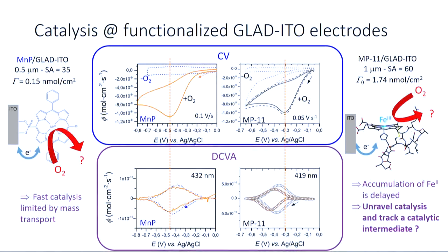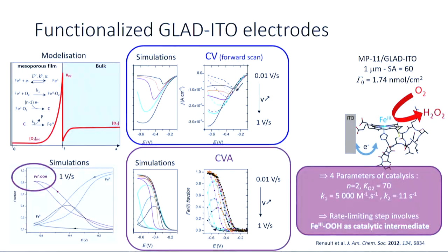And I will show you that this now allows us to unravel the catalytic process and track reactive and catalytic intermediates. So I have to make a long story very short, I'm sorry for this. We investigated by cyclic voltammetry and cyclic voltabsorptometry the catalytic process at different scan rates, up to 1 volt per second, and you have very specific shapes here, especially for the accumulation of iron 2 in the nanostructured electrode. We developed a model, and we were able to fit, or to simulate, all the experimental data, to extract 4 parameters characterizing the catalytic process, including the stoichiometry of the process, allowing us to conclude about a 2-electron reduction to hydrogen peroxide by this iron porphyrin.